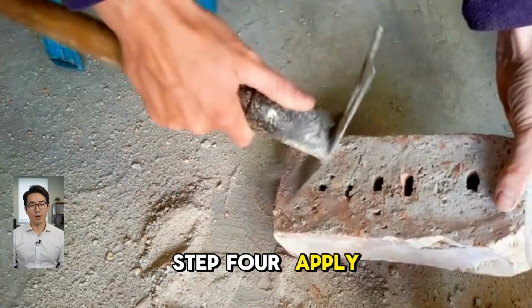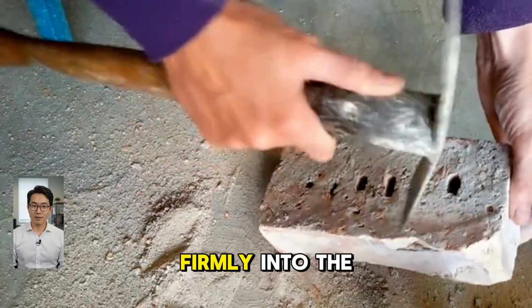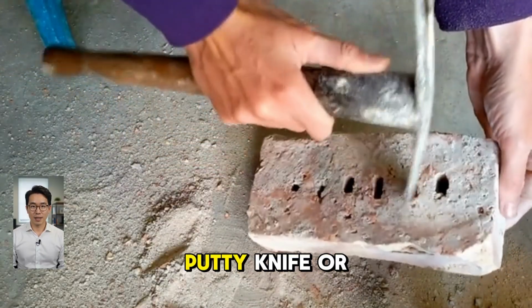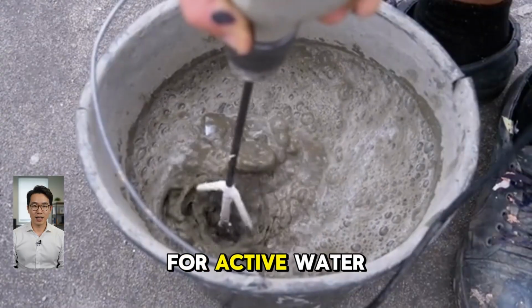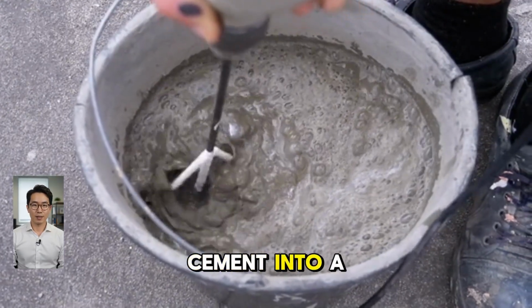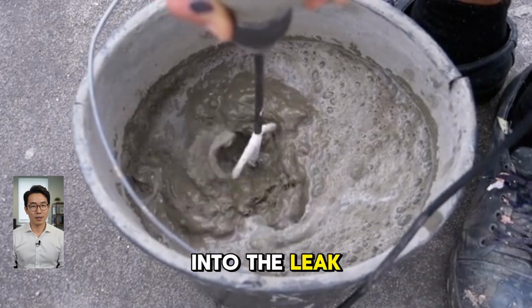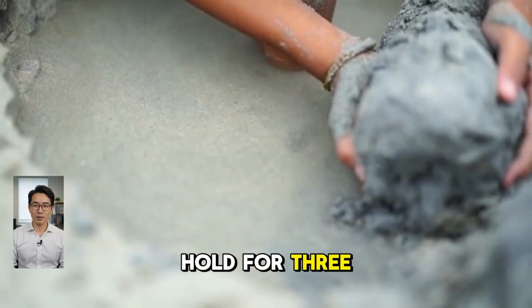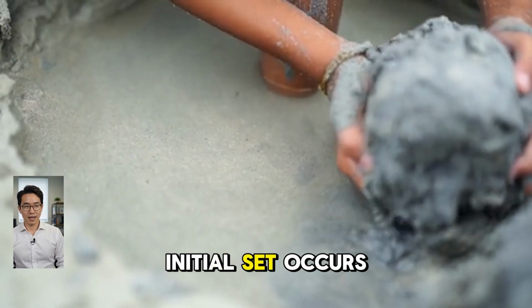Step 4, apply immediately. Press the mixed cement firmly into the crack, packing it tightly with the putty knife or your gloved thumb. For active water leaks, form the mixed cement into a cone shape and hold it pressed into the leak point with your gloved hand. Hold for 3 to 5 minutes until the initial set occurs.